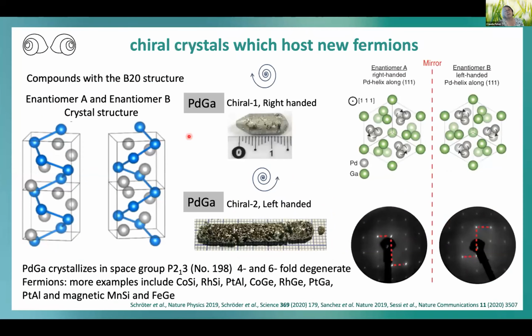So we were able to grow 2 of these compounds, and the compounds are very familiar to many of you because it's manganese silicon, and iron germanium belongs also to this compound. From palladium gallium we could grow 2 different chiralities of the crystal. This was hard work and a little bit of luck, so where we can really then investigate the difference in 2 enantiomers.